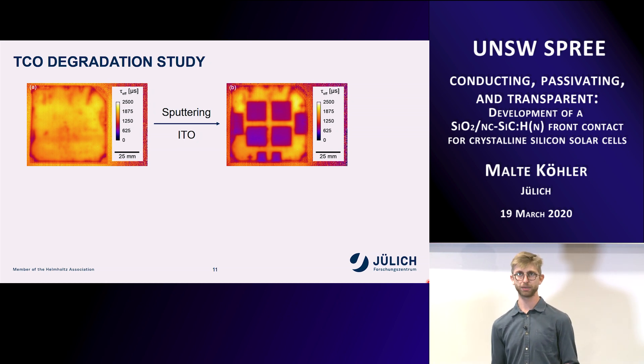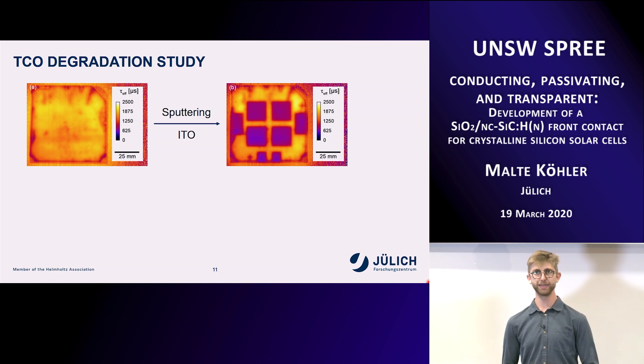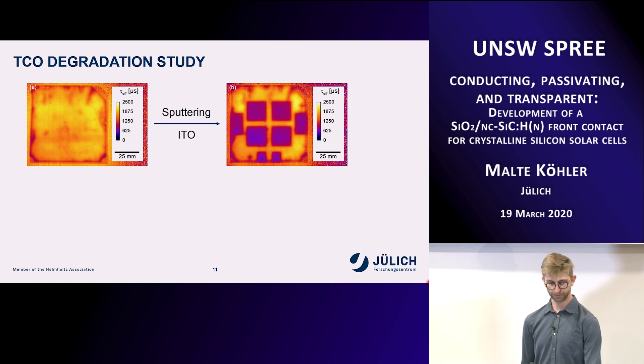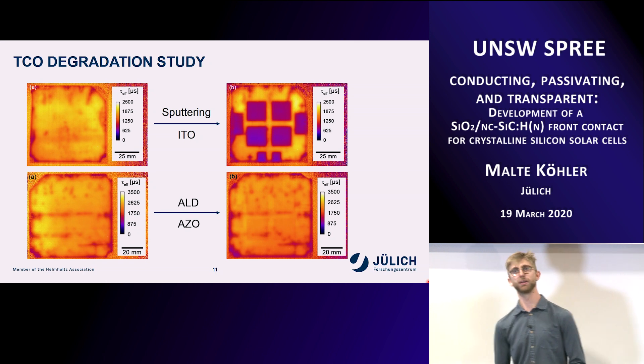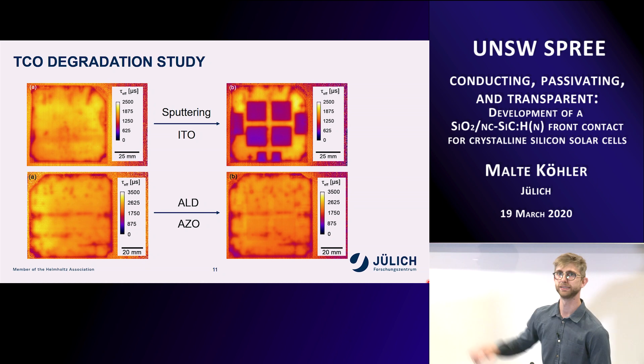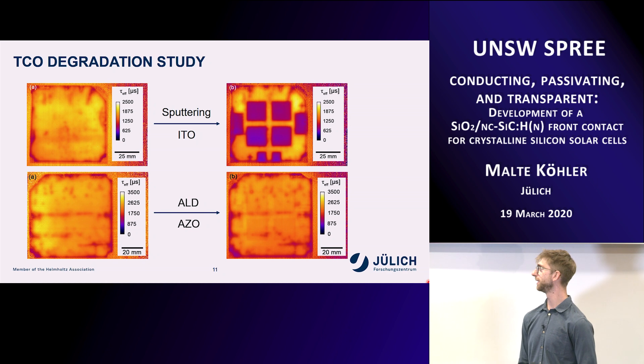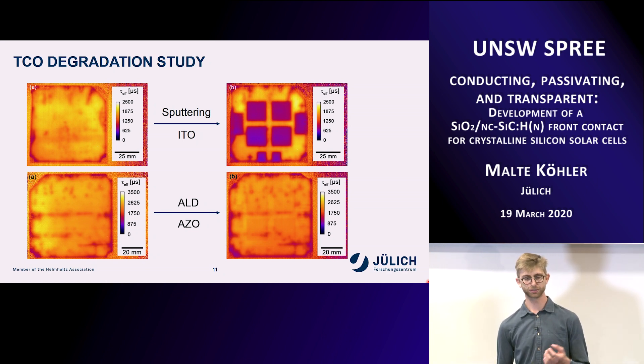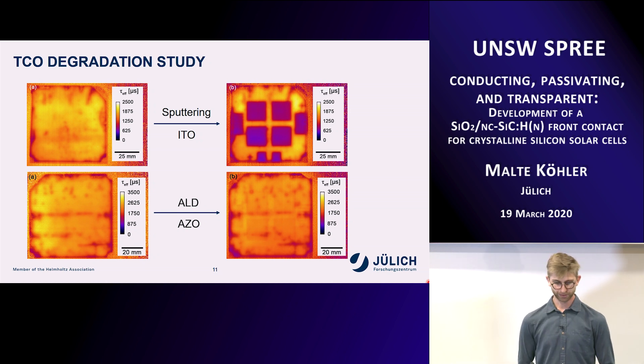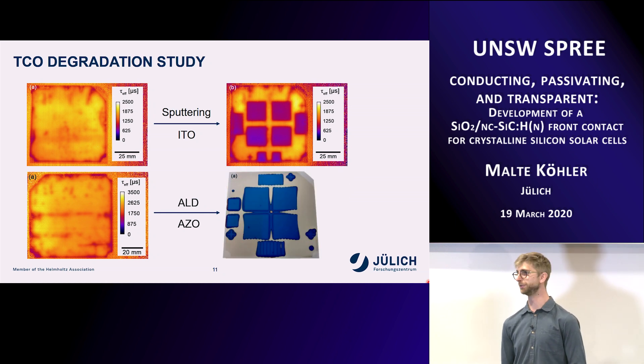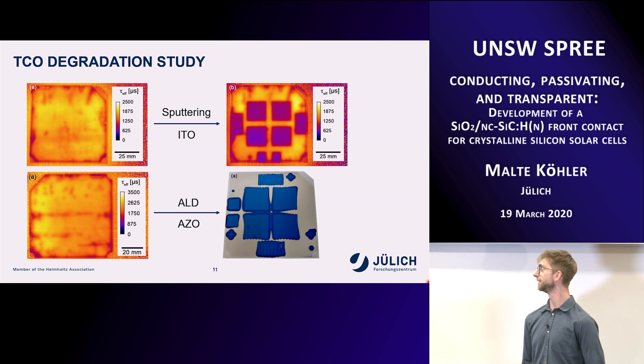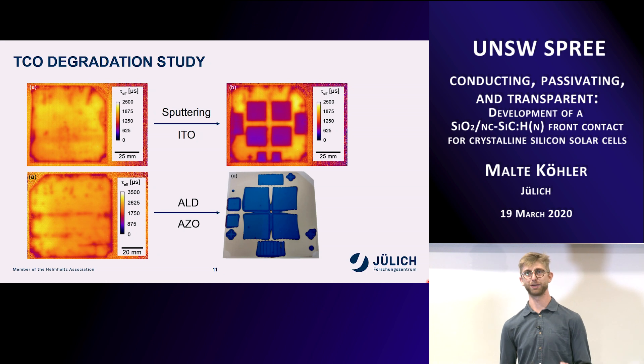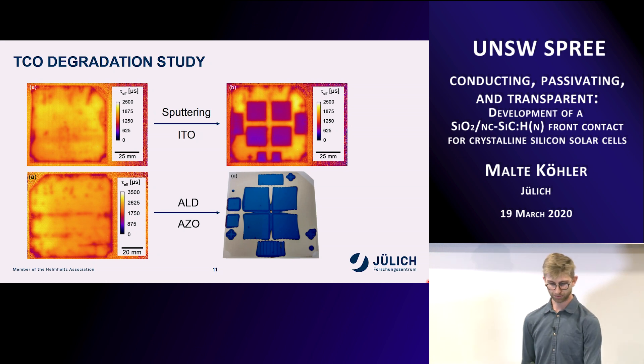We tried ALD since it involves neither ion bombardment nor UV damage. AZO was available, so we deposited AZO by ALD and saw no degradation at all — only very slight degradation attributable to ITO on the backside amorphous silicon. However, when you use ALD with a mask, the gases creep underneath the mask and form the layer also between solar cell areas we designed. So you end up with another problem: you have to disconnect these AZO regions again by etching away. So that was also not the ideal solution.